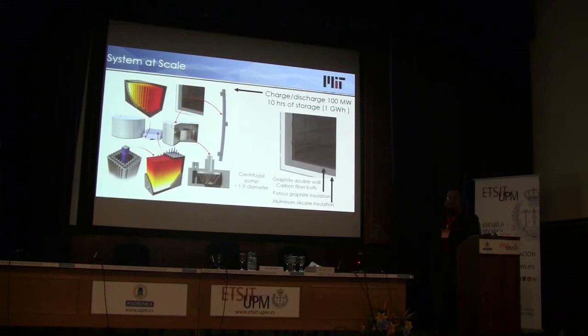So we're in a regime where the amount of pumping power is effectively negligible, but this is presupposing that your pump is in the regime where you're at tens of percent, you're at 80, 90% pumping efficiency. Electromagnetic pumps are often less than 1% efficient. When you get that low, the pump itself becomes just a heater, and since we need to put heat in electrically, imagine some kind of coupled system that does that, but you'd have a serious challenge.